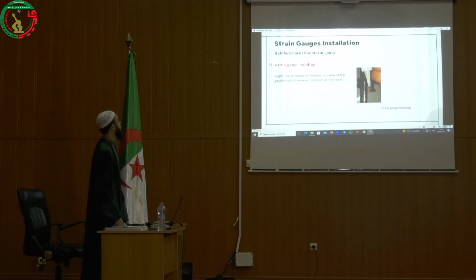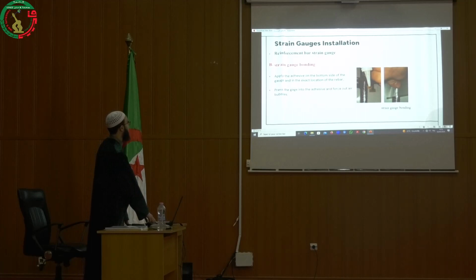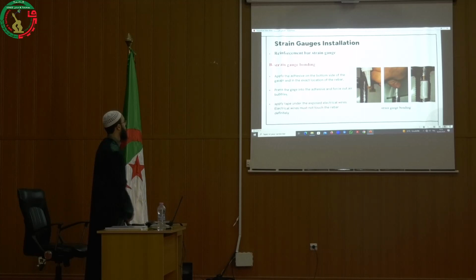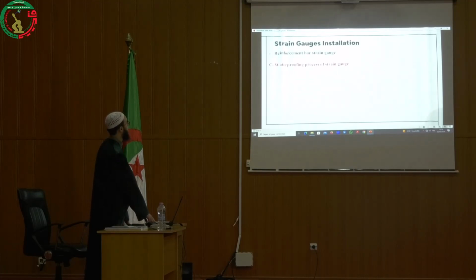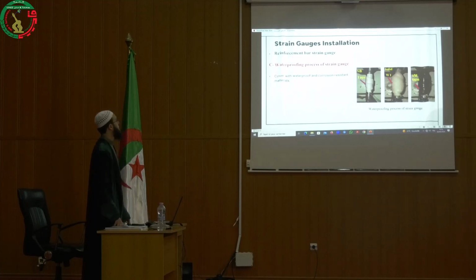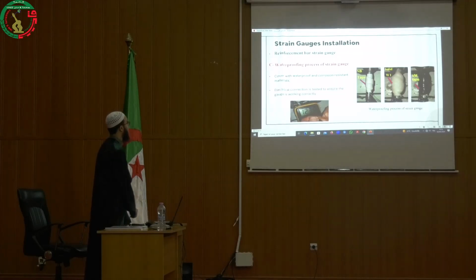After cleaning the bar, we apply the adhesive on the bottom side of the gauge and in the exact location of the bar. Then we press the gauge into the adhesive and force out air bubbles. Then we apply tape under the exposed electrical wires, because these wires must definitely not touch the rebar. Then we cover the gauge with waterproof and corrosion resistant materials. And finally, we check the electrical connection to ensure that the gauge is working correctly.